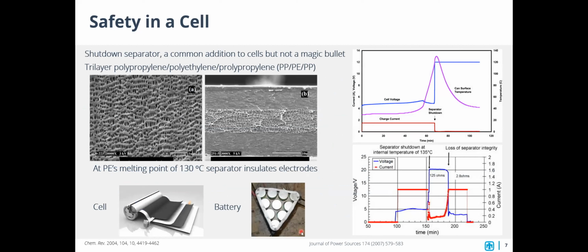So what do we actually put into a battery to make them safer? One thing that exists in a lot of lithium and lithium ion cells is what's known as a shutdown separator. A separator is the electronically insulating portion that separates your cathode and anode, usually just a porous polymer, imaged here. A shutdown separator is a tri-layer polymer, where you can see the cross section here, where the center layer, typically polyethylene, will melt under high heat around 130 C. When it melts, it will clog the pores of this separator, stopping any ion transport. And this is important because if you stop ion transport, you can stop the flow of current.